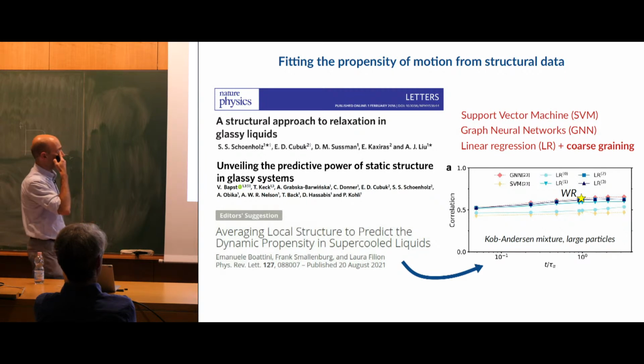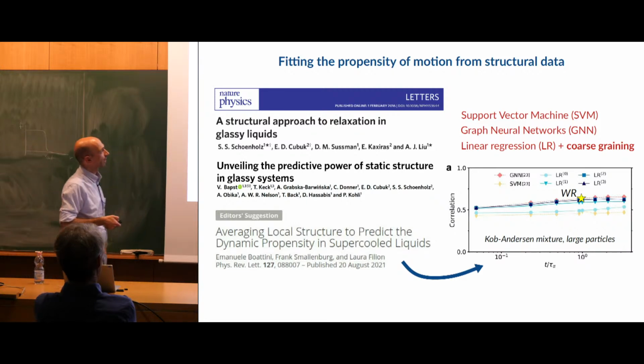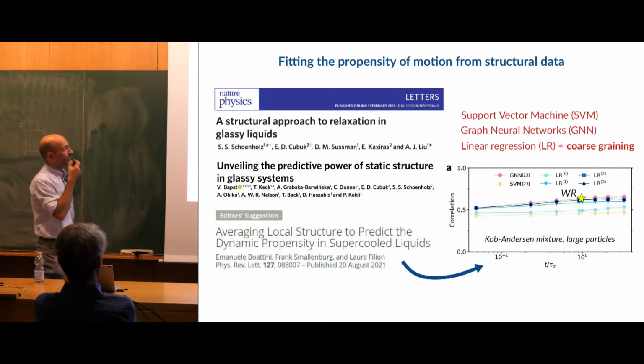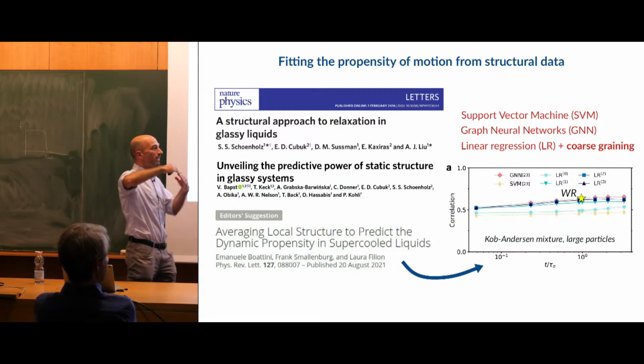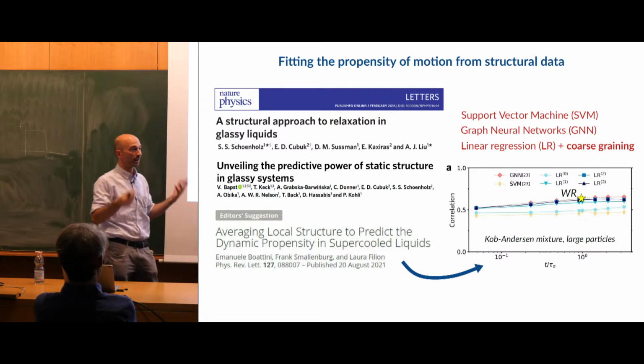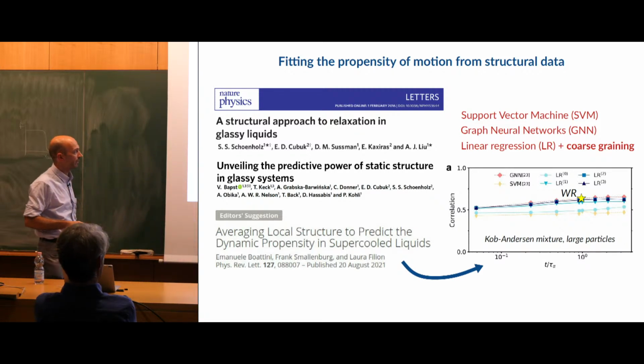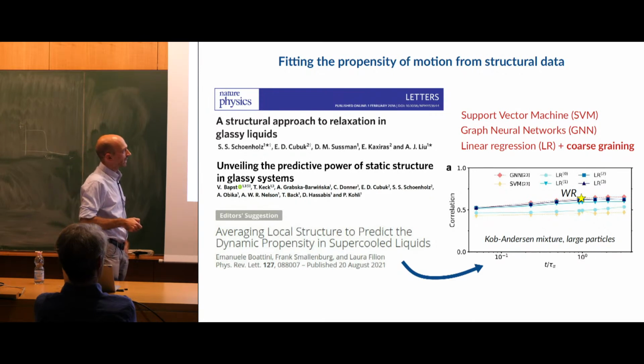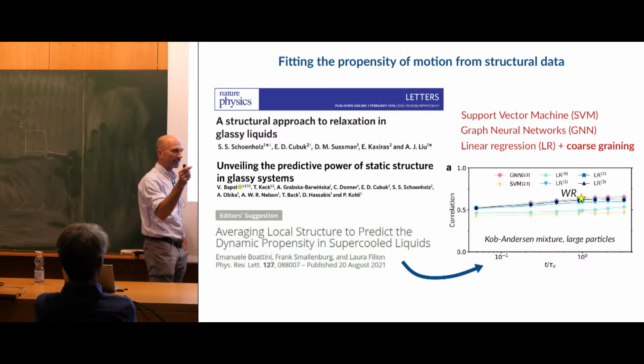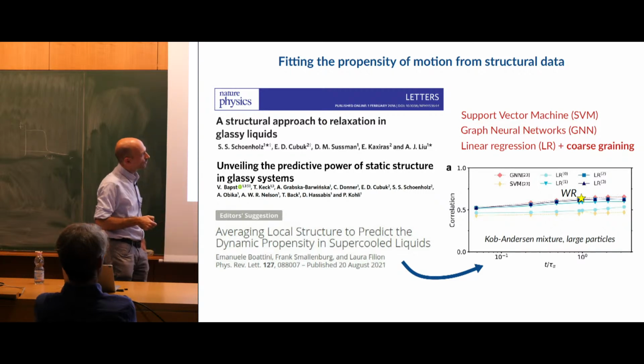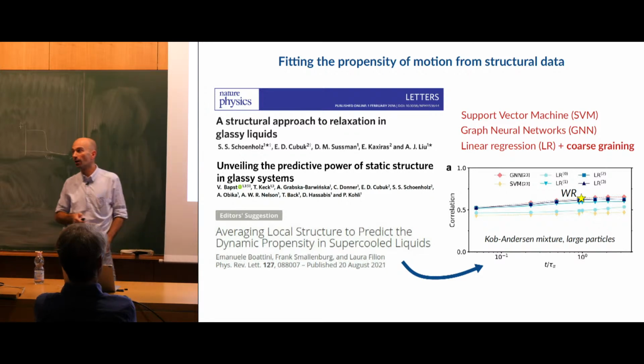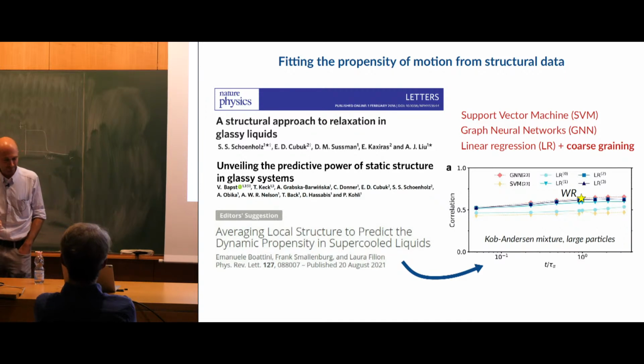This was pioneered by Andrea Liu and co-workers with the support vector machine. Recently, there have been more sophisticated methods like graph neural networks. And Laura this morning told us that using a simple linear regression plus this spatial averaging, we get results that are on par with these more sophisticated methods. As we can see here, for the Kob-Andersen Lennard-Jones mixtures, which is one of the hardest benchmark cases for this kind of measurement, I would say. So these two methods currently set what I would say is the world record for the correlation of this model around the structural relaxation time.